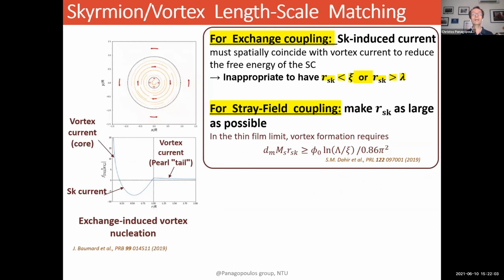So if I am to match the skyrmion or the magnetic vortex with the superconducting vortex, then I would need to match the length scales. If I want to have exchange coupling, then the skyrmion-induced current must spatially coincide with the vortex current in order to reduce the free energy of the superconductor. And therefore, it would be inappropriate to have a skyrmion whose radius is smaller than the coherence length of the superconductor, or a skyrmion whose radius is larger than the magnetic penetration depth in the superconductor.